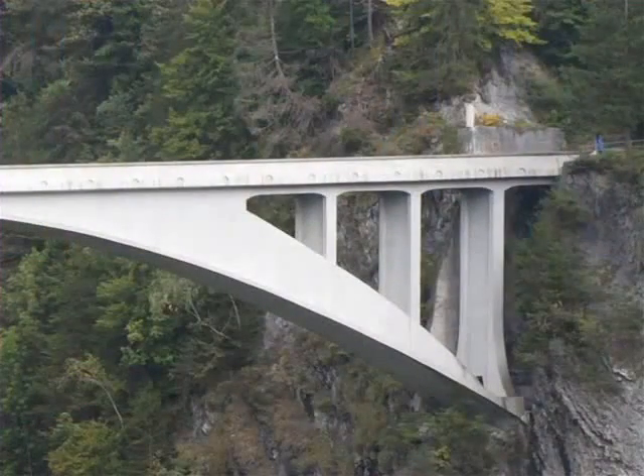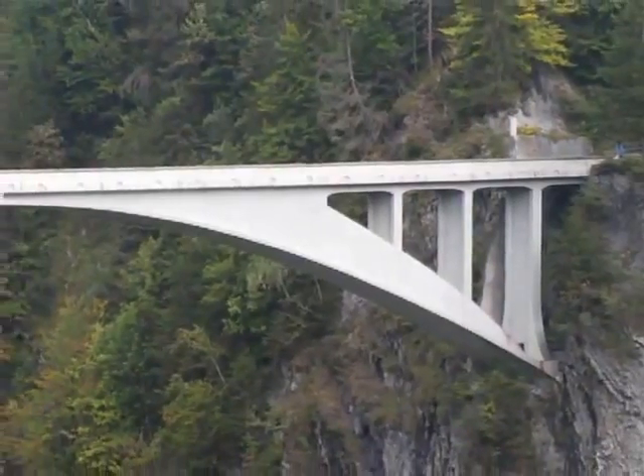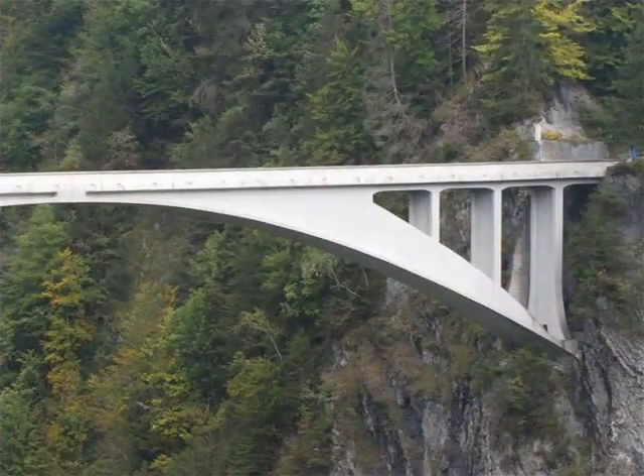2 years later, Maillart learned that the spandrel walls of his Zuoz Bridge had experienced significant longitudinal cracking. What most engineers would have regarded as a failure, Maillart saw as an opportunity. After a careful analysis, he recognized that those cracks in the spandrels didn't affect the structural integrity of the bridge. And indeed, they showed that the spandrels weren't really part of the main load path. So he reasoned that he could simply remove most of the material in the spandrels in future designs. That insight led to the extraordinary form of the Salginatobel Bridge.